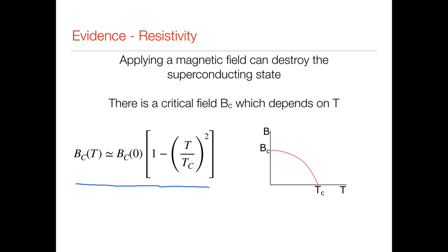So this is temperature on this axis and magnetic field applied on this axis. If we were very close to zero temperature, we would have a critical field BC. But as I go to a higher temperature, my critical field becomes lower, so it becomes easier to destroy the superconducting state. So very close to TC, only a very small magnetic field can be withstood before the material is driven to be normal. If you think about this as a little bit like a phase diagram, you could think about this region here as the superconducting region, and outside here is the normal. So that was found experimentally fairly early on, that the magnetic field can destroy the superconducting state.